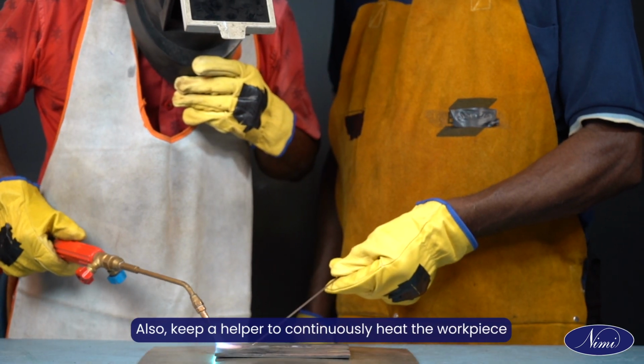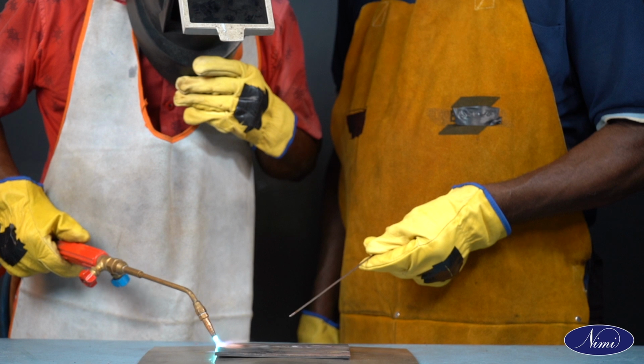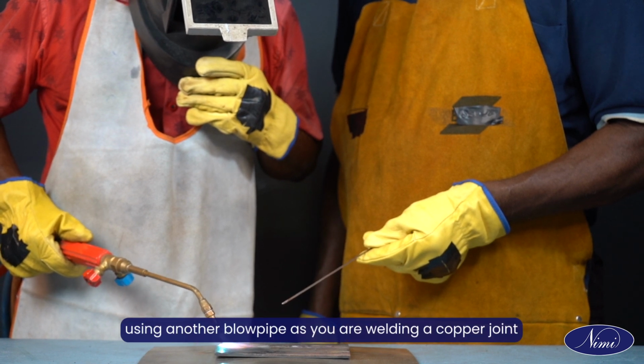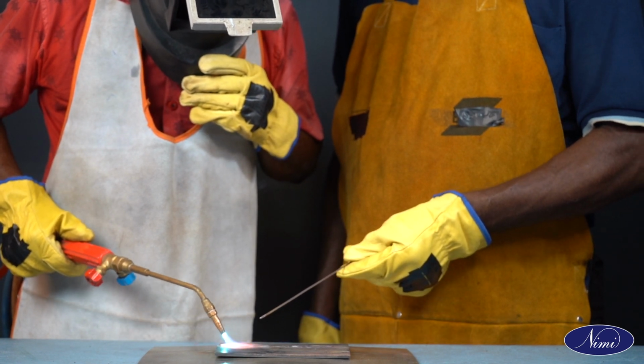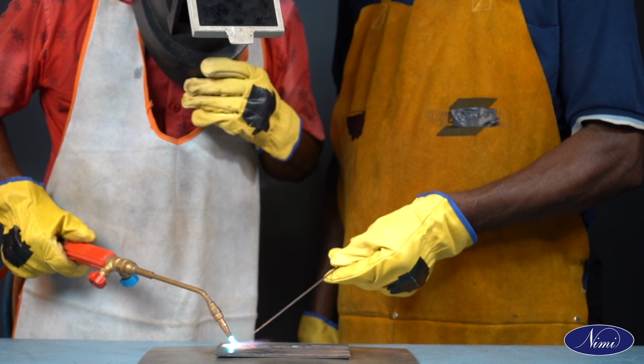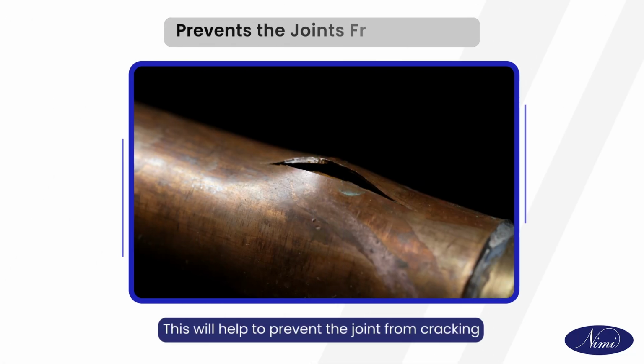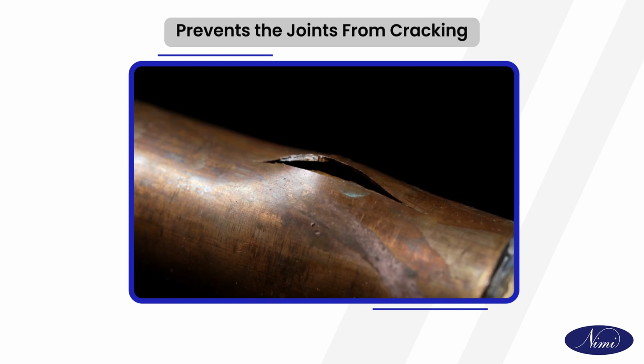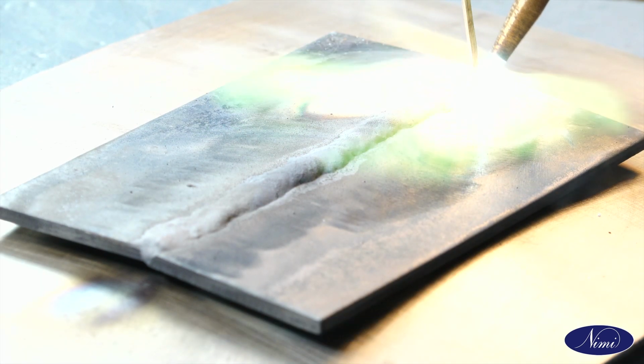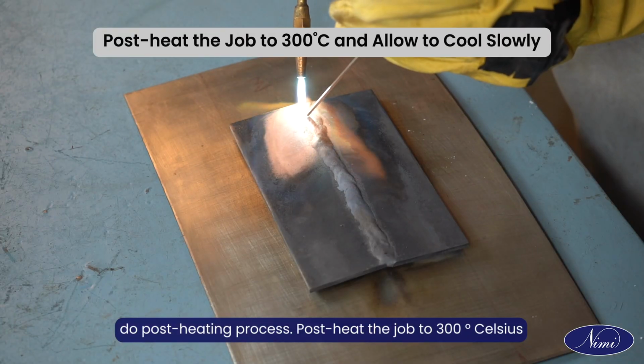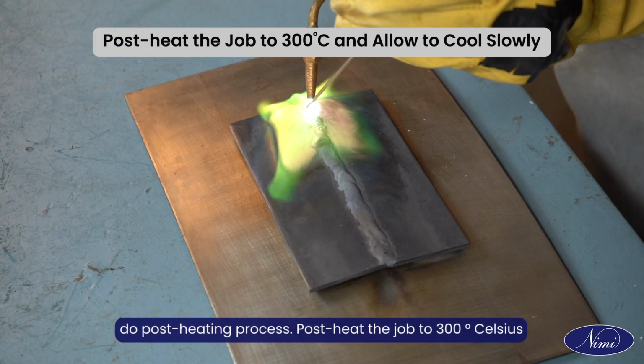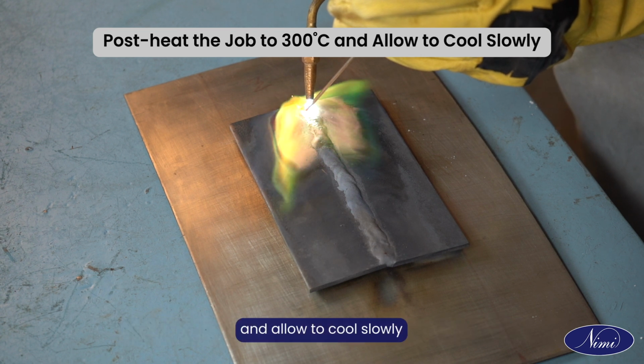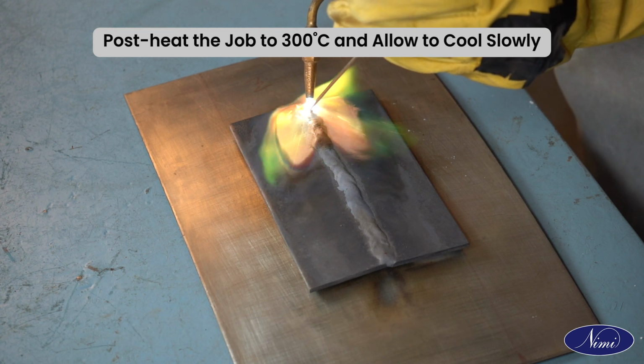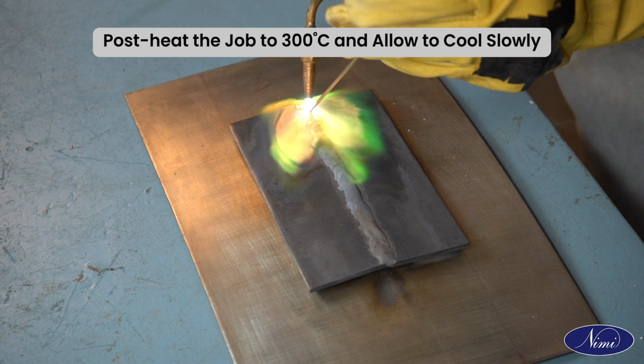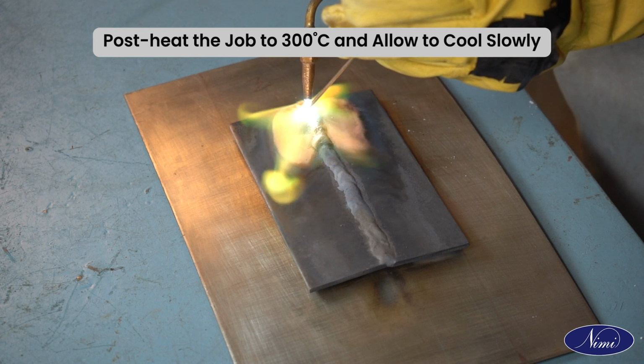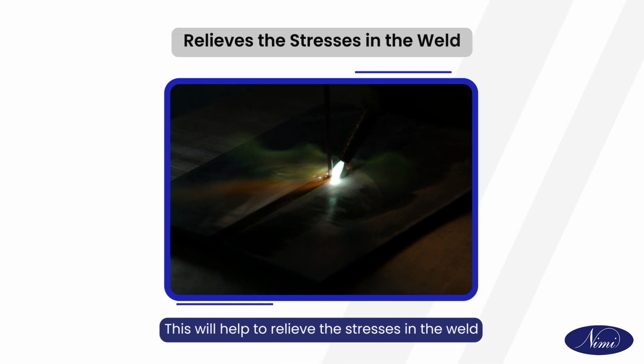Also, keep a helper to continuously heat the workpiece using another blowpipe as you're welding a copper joint. This will help to prevent the joint from cracking. Once the procedures of welding are done, do the post-heating process. Post-heat the job to 300 degrees Celsius and allow it to cool slowly. This will help to relieve the stresses in the weld.